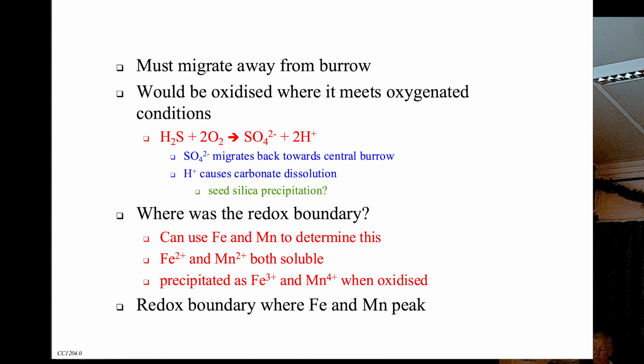When we actually reach oxygenated conditions, another group of bacteria will attack the H2S with oxygen and oxidize it back to sulfate. That sulfate can then migrate back to the burrow, get used again, and the carbonate this releases in time will actually cause precipitation of silica. And we know we've got a lot of carbonate coming from dissolution of chalk where the flint forms. This is telling us that we should be precipitating flint in the same region.